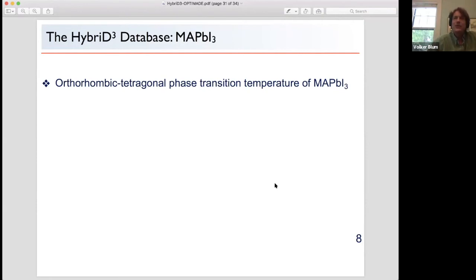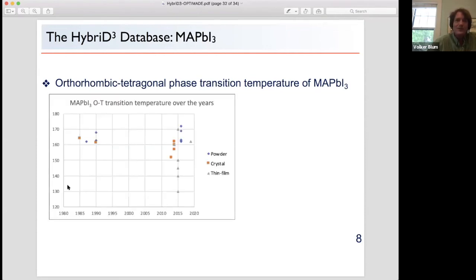One thing I said initially is that there's a lot of data out there, but you don't know how good it is. Right? And this is in fact true even for MAPbI3, which is most likely the best studied organic inorganic hybrid perovskite on the planet at this point. It has three phases, orthorhombic, tetragonal, and cubic. But if you focus on this orthorhombic tetragonal phase transition, for which the temperature should be well known, it turns out it is. Many people have measured this. And so this is over the years, the phase transition temperatures that we have in the database. And if you just plot these phase transition temperatures, and all of them were measured for good reasons, if you plot these, you find a large scatter.